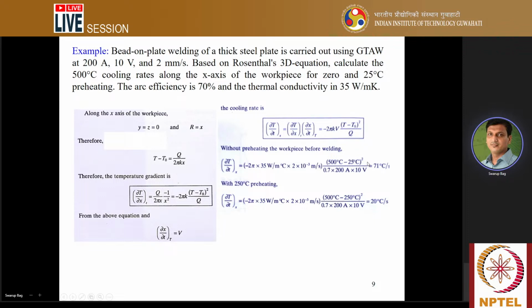(T minus T0) squared divided by Q. How to calculate the Q? 0.7 is the thermal efficiency into ampere into voltage. Once you calculate, you'll get the cooling rate equal to 71 degree centigrade per second. Now, if it is preheating, that means the initial temperature is not the ambient temperature, the sample is preheated. Similar calculation here, 500 degrees centigrade minus 250 degrees centigrade, because this is the preheated temperature. Got it? Then we get 20 degrees centigrade per second.